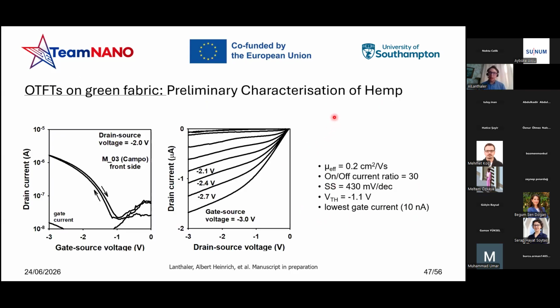Showing some preliminary characterization for the hemp device here, as you can see, we were able to achieve the lowest gate current among the others, in the 10 nanoamp range. The mobility is comparable with other TFTs fabricated on gelatin, 0.2 cm²/V·s. The on-off ratio is 30, which is not the greatest compared to the others, and we cannot see an entirely well-defined saturation area for the output characterization here.